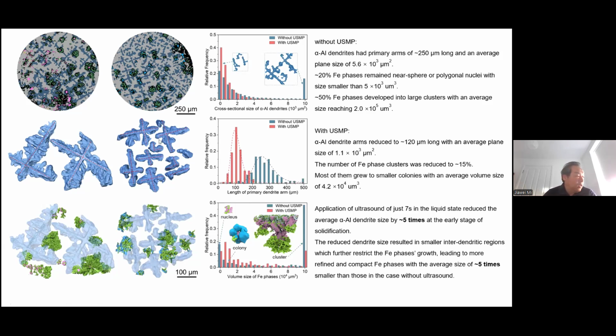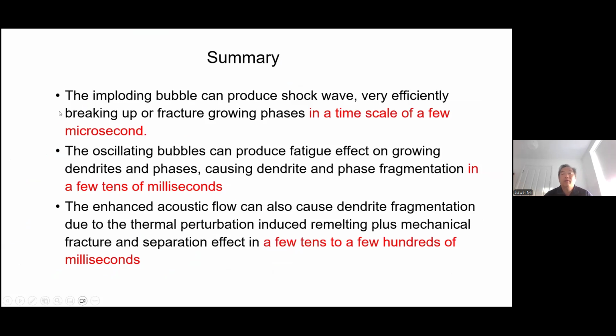I think the time is passing quickly, so I will give you a summary. In terms of ultrasound processing, there are 3 mechanisms that can help change the structure of the materials. One is that bubbles can create local shock waves, which very effectively fragment these growing phases on a time scale of just a few microseconds. But the oscillating bubbles can also produce a fatigue effect and can break off the dendrite, causing fragmentation, again on a relatively longer time scale, in tens of milliseconds.